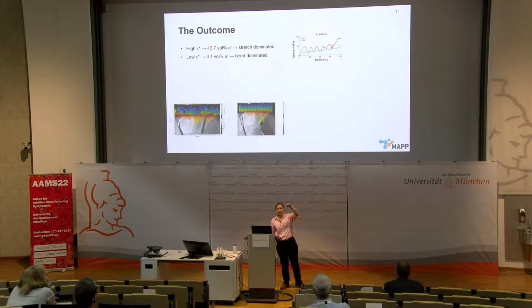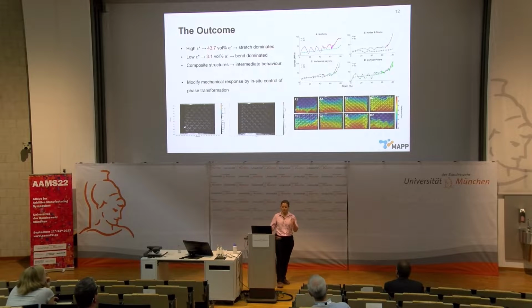So you can see it takes the load, collapses, takes the load, collapses. The low strain parameters then, with very little martensite in them, we see a nice bend-dominated structure, which is the one people are normally looking for. But this is where the whole structure takes up the load and then it just squashes gently as a complete thing. But what about all these composite ones we made? So, with the composite ones, we see intermediate behaviour. The nicest one I think probably is the horizontal layers, the C graphs, where we see some plateau behaviour and then we see some collapsing behaviour as well.